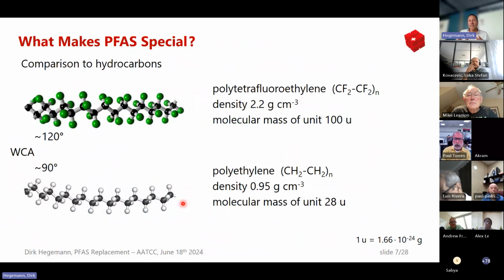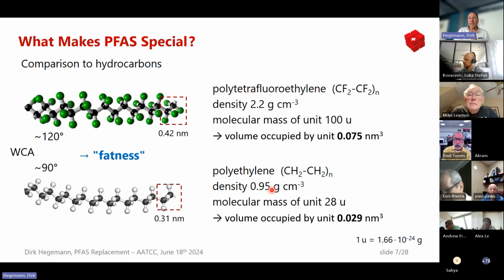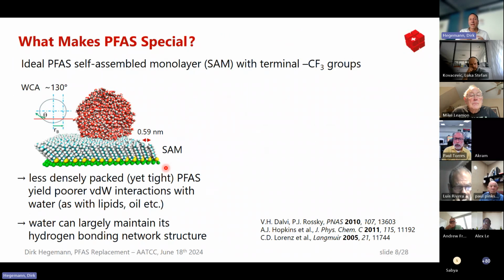Another aspect, not only surface energy, is that when you compare PTFE to polyethylene, it has a higher density. But when you look at the volume occupied by a unit, the CF2 group, it occupies a much larger volume than the corresponding CH2 group. In the literature, this is known as fatness. So the fluorocarbon functional groups contain a lot of space, and that adds to the important characteristics of PFAS.